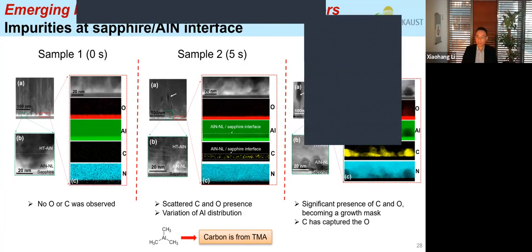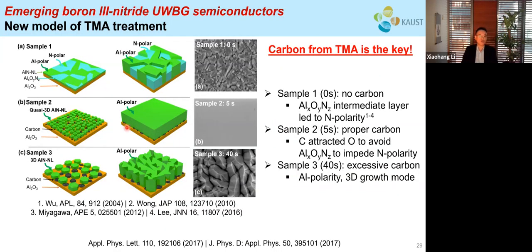So this also means that if we grow aluminum nitride on top, essentially we are not growing on a flat sapphire substrate, but we are growing on a very rough surface with different carbon islands. So it's like a growth mask. But the coexistence of oxygen and carbon indicates that the carbon has captured the oxygen, which actually prevents the formation of nitrogen polar aluminum nitride. So based on our study, we have proposed a new model to explain the trimethyl aluminum treatment of the sapphire substrate. And we note that the carbon from the trimethyl aluminum is the key here.